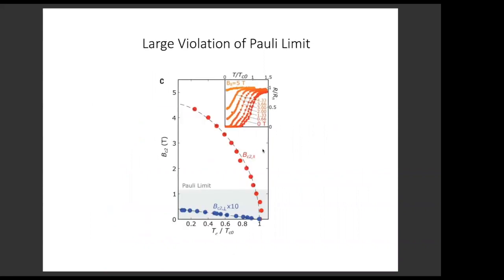Also, regarding the triplet nature, the experiments actually already observed back in 2018 a very large violation of the Pauli limit. When you apply an in-plane critical magnetic field, the superconducting state survives even when the critical field is much larger than the Pauli limit. Of course, there are other scenarios where this large Pauli violation can be explained, but this is certainly consistent with triplet pairing.